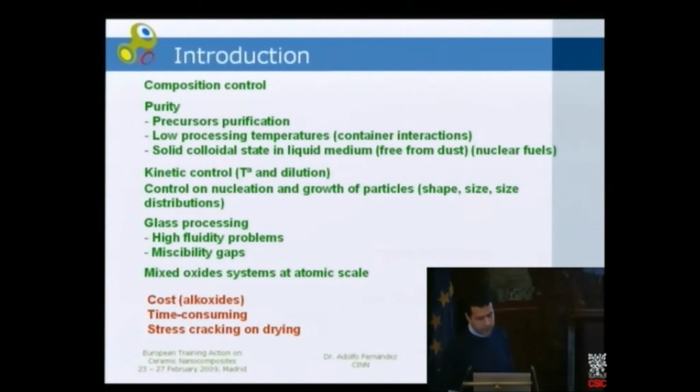Another possibility is the control of the kinetics of the reactivity of the precursors by controlling the temperature and the dilution. The control on the nucleation and growth of the particles allows the obtention of particles with controlled shape and size and with suitable size distributions. Concerning glass processing, the sol-gel method is a solution for high fluidity problems or for miscibility gaps in determined compositions. And the characteristic of the sol-gel itself is that it allows the obtention of mixed oxide systems at atomic scale.